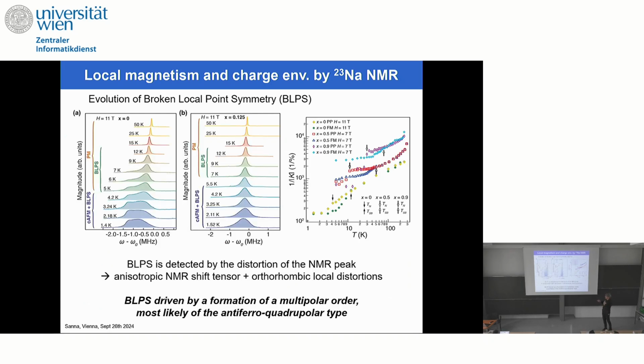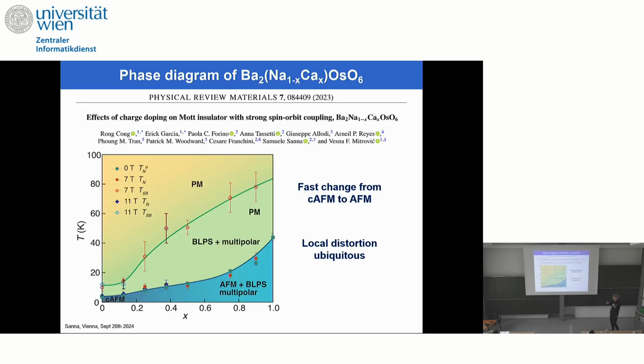Anyway, this way we could detect through the distortion of the NMR peak that there is an anisotropy in an NMR shift tensor, which has orthorhombic local symmetry, which we interpret as the formation of a multipolar order, most likely of antiferromagnetic quadrupolar nature. And we could map the phase diagram that was already shown in the previous days, also by Arun the first day, where here we have the transition from the symmetric line shape of the NMR signal, let's say cubic static condition, to this static distorted phase, anticipating the magnetic transition.